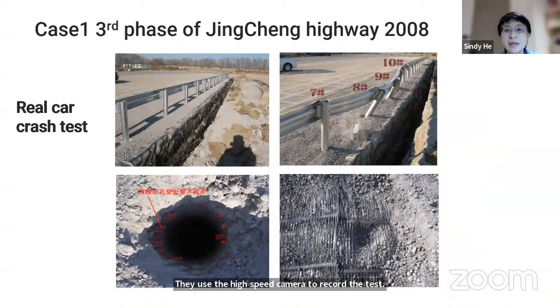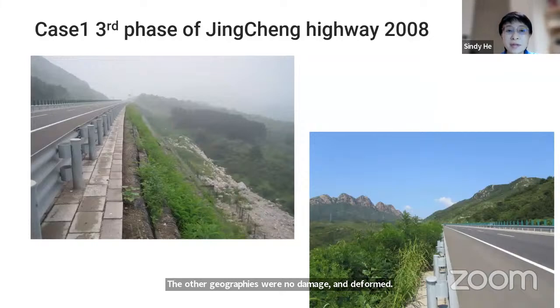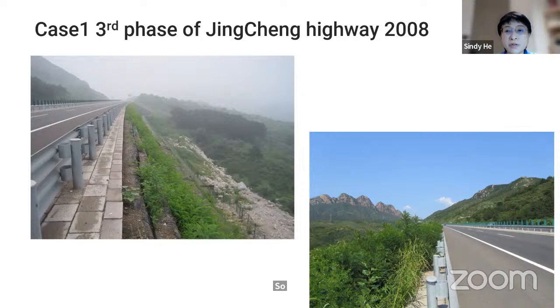After the test, the slope seems to have no movement. Some steel guardrail moved, but only a small amount, except where the steel guardrail was driven. The other geogrids were not damaged or deformed. So finally, the steel guardrail was used on the top of the reinforced slope and saved a lot of money in this project.